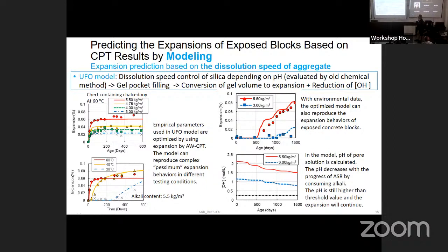This chart shows this kind of complicated behavior. At higher temperature, according to alkali concentration, like this. So the model will reproduce this behavior. And temperature dependency was complicated. For this, we applied some Arrhenius plot. Then we introduced some temperature dependency, some basic parameters. Then this model was with the optimized parameter.